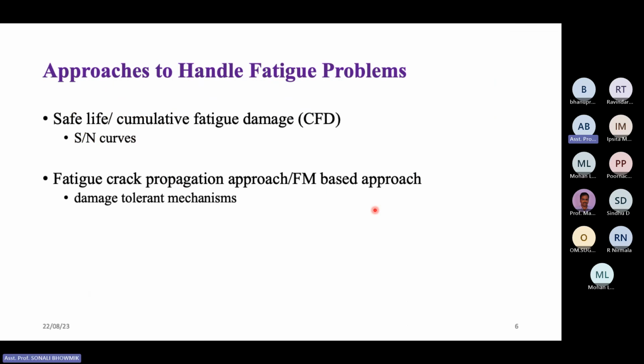So how do we handle those fatigue type problems? As I mentioned, in the area of metallic structures like steel or other alloys, in the field of aerospace engineering, people are working extensively, and S-N curves are one approach through which one can find out the fatigue life, and this is well established. But the S-N curve is not fully valid for structures like concrete. I'm not going deep into S-N curves because what I specify here is limited to concrete.